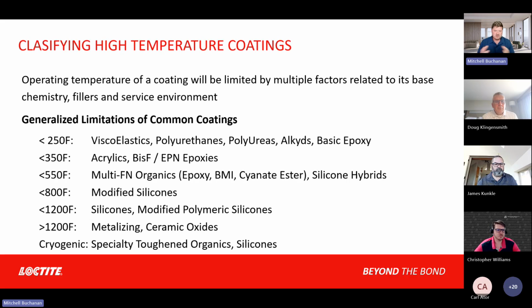So when we look at temperature, how do we classify high temperature coatings? And then this is the Mitch version of this, right? Someone probably has different definitions, but this is how I think about it. And different chemistries are going to peak at different temperatures, right? Of note, because I've included it in the first three sets there, would be epoxies, right? Epoxies, ubiquitous organic coating. Your basic epoxies, like your JB Weld type, two-component epoxy, your Mercaptan Cure epoxies, are going to typically have a maximum service temperature around 250 degrees Fahrenheit.